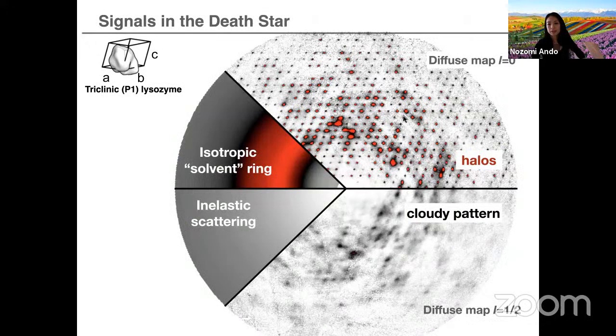And so if we were to take a slice through that Death Star and look at all the different components of the signals in there, there are some things that are expected. There's inelastic scattering, which we subtract out, the isotropic solvent ring, which is a contribution of both solvent and protein, but centered around 3 angstroms. And then the diffuse scattering, the variational scattering. And within the variational scattering, there are two types of signals. Caspar and Clarage and the rest of the field had long called the cloudy diffuse scattering, as well as these bright spots that were becoming really apparent, and we called these halos.